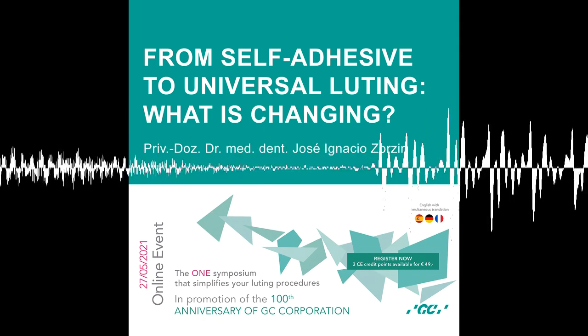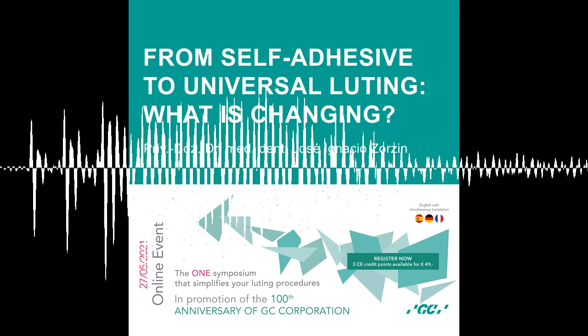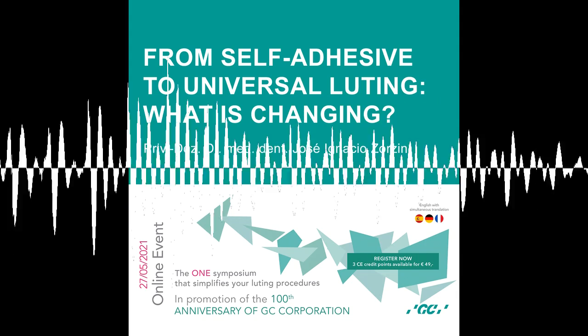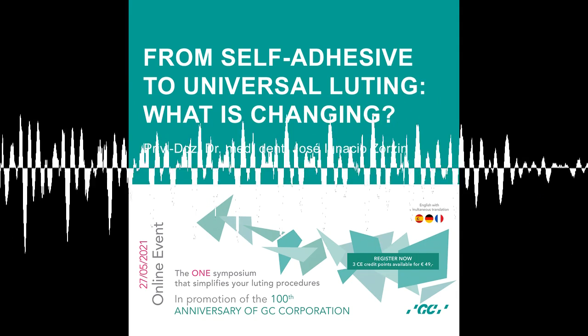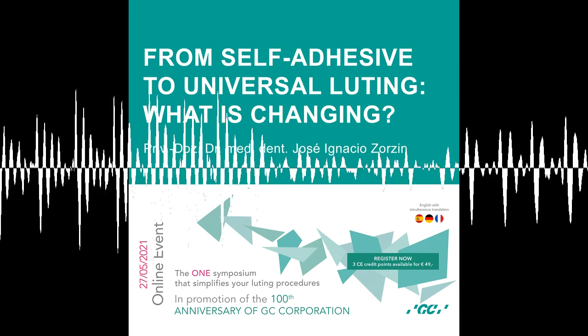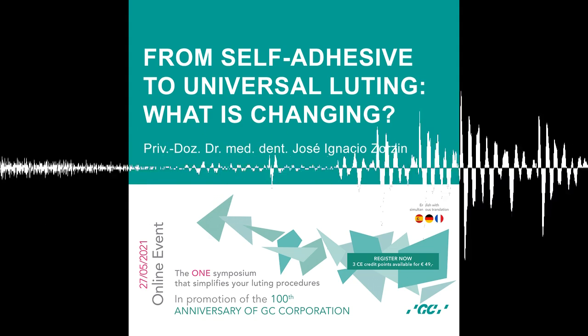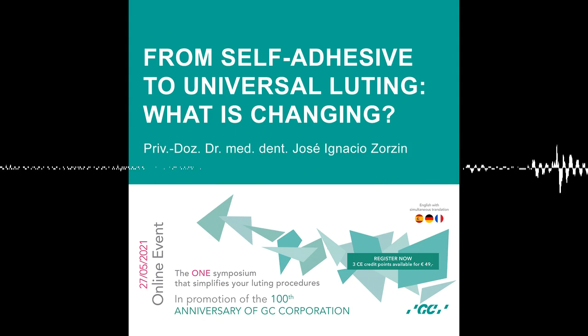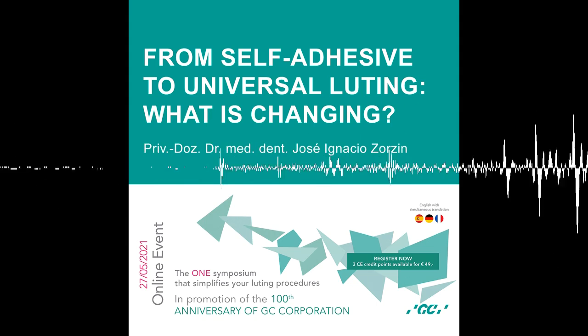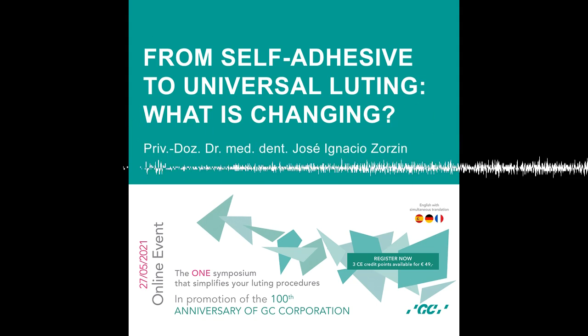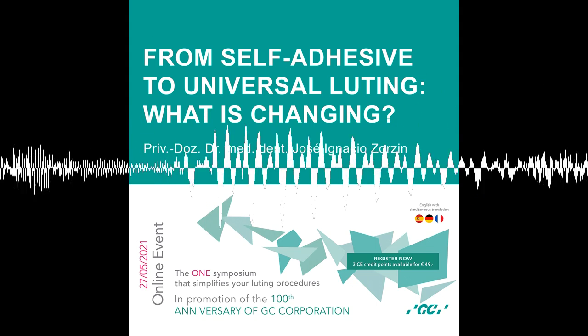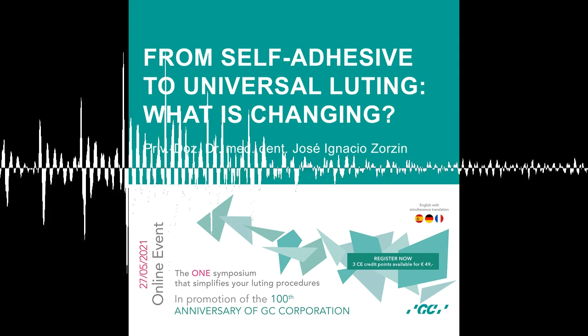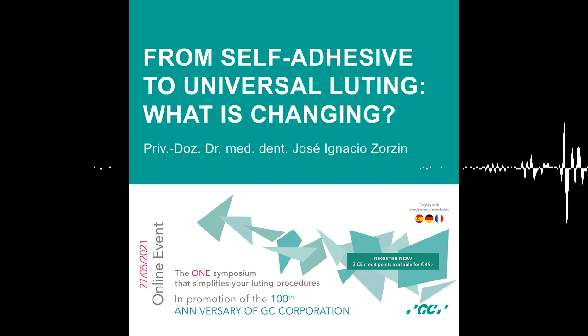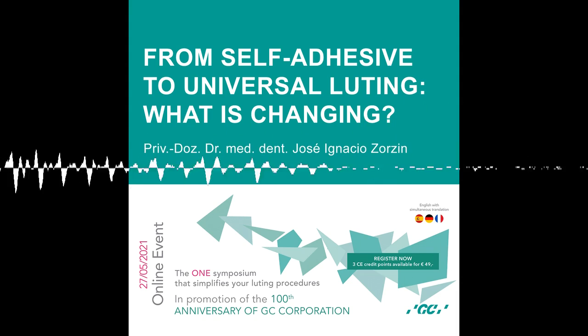Of course, always when we do luting, it's important to try to keep the operation field dry, to try to keep away saliva. Saliva is a terrible contaminant which inhibits the adhesion massively. And the problem with saliva is because of its polarity, it sticks very firmly to both substrates. So always be careful. Using rubber dam when possible is important.